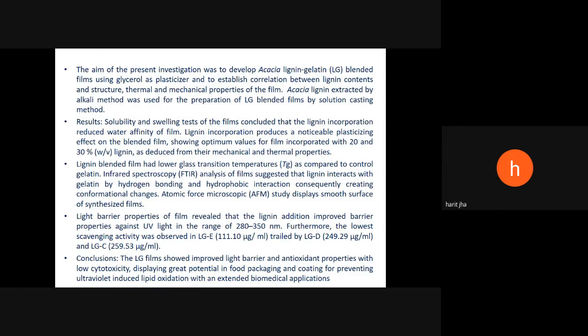Lignin blended film had lower glass transition temperature as compared to controlled gelatin. Infrared spectroscopy analysis of the film suggested that lignin interacts with gelatin by hydrogen bonding and hydrophobic interaction, consequently creating conformational change. Atomic force microscopy study displayed smooth surfaces of the synthesized film.